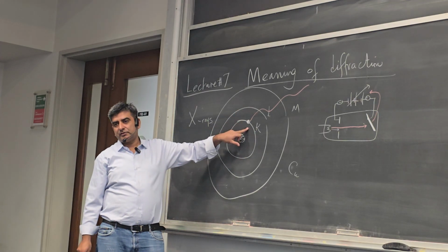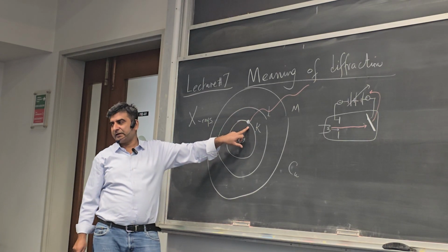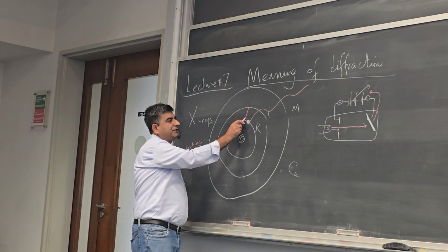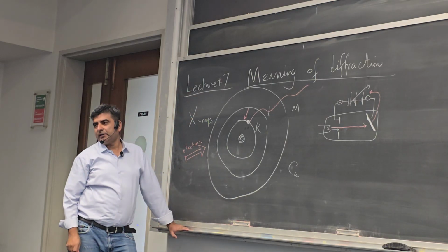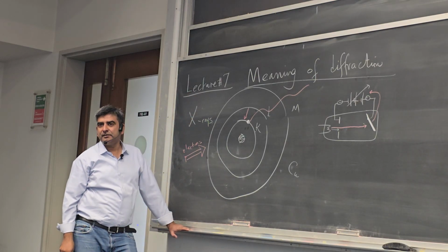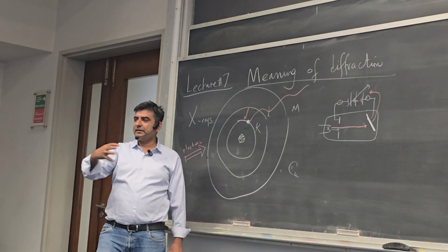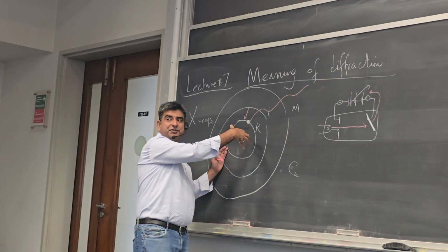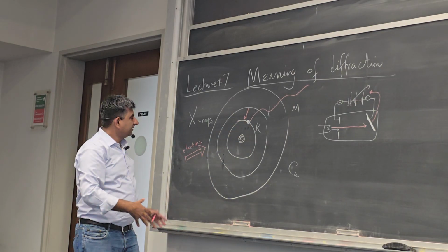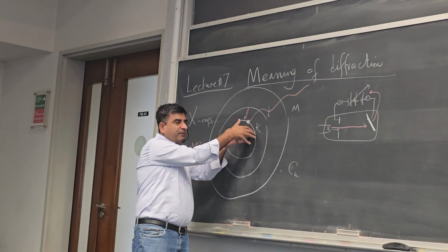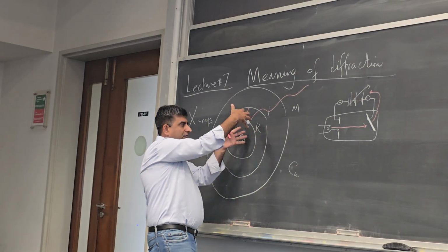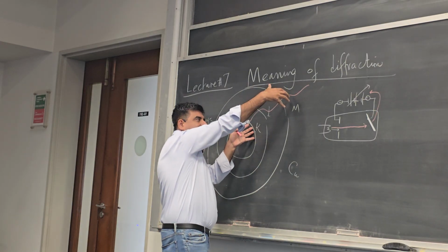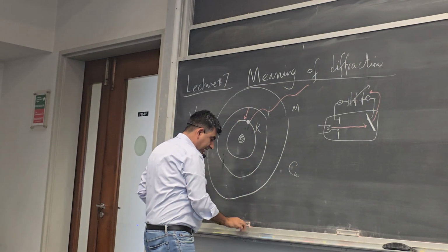Some higher electron in a higher shell falls down to fill up this vacancy. For example, an electron from an L shell can fall into this vacancy, and when it does so, it emits electromagnetic radiation. Since this is a big atom and this is an inner shell being filled, the electrons have knocked off an electron from an inner shell, not from a valence shell. So a vacancy has been created in the inner shell. Higher excited electrons, from some higher state, fall down and emit radiation.